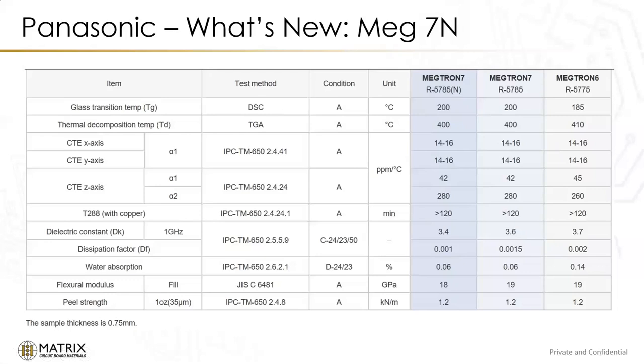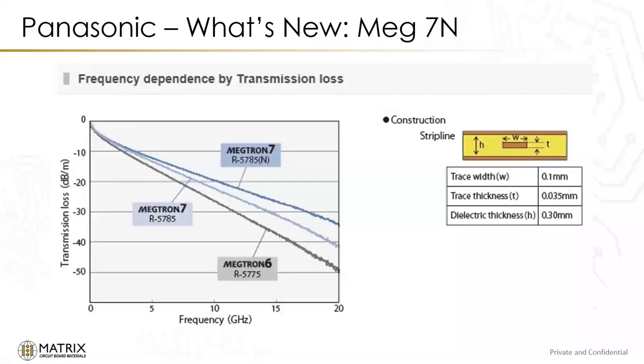If we look at the loss factor as it compares, you can see that the MEG 7N, as far as we're looking at dB loss per, in this case, per meter, there's less loss. The higher on this chart it is, the less loss across frequency with MEG 7N. The next on it would be MEG 7. Of course, the MEG 6 is here. So we get good transmission signal performance with MEG 7N.